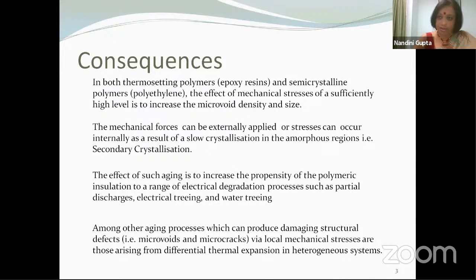It can give rise to electrical trees. It can give rise to partial discharges. And as I told you, partial discharges in themselves lead to degradation process and stress mechanisms in the dielectric. Another thing that we have not talked about is water treeing. Water trees are similar to electrical trees, except that they need humidity or water to be able to grow. And water treeing, in addition to electrical treeing, is one of the important pathways to break down over time.